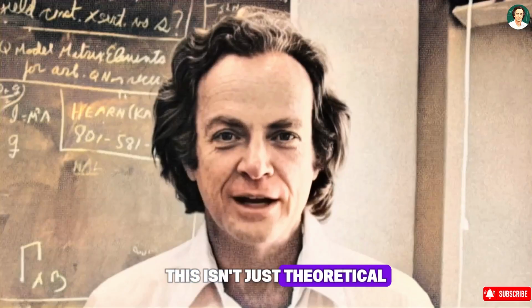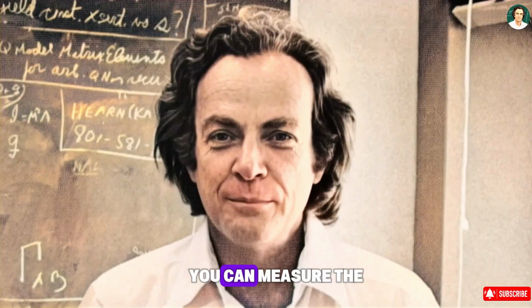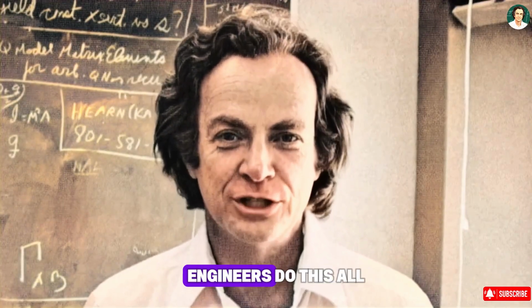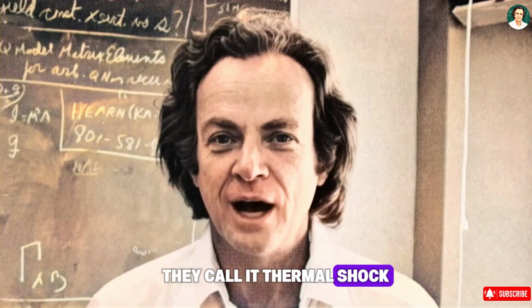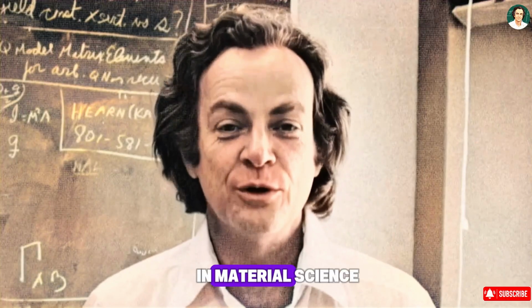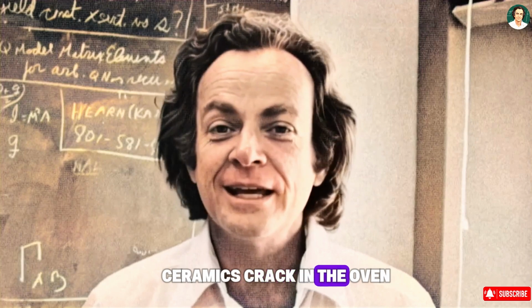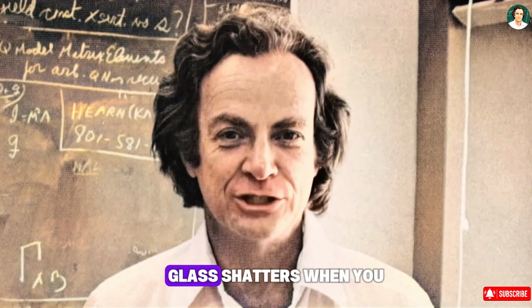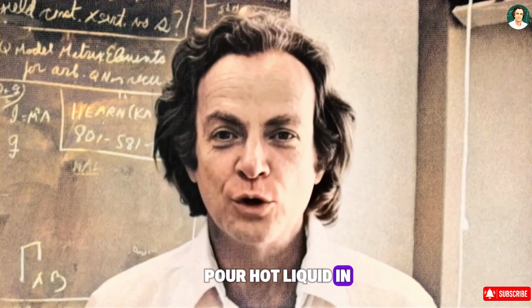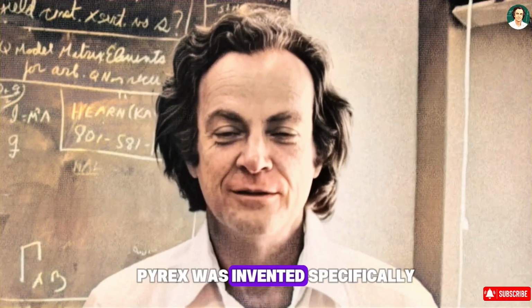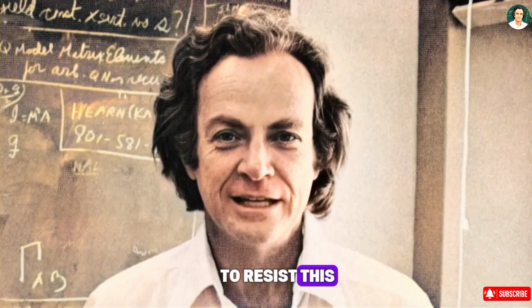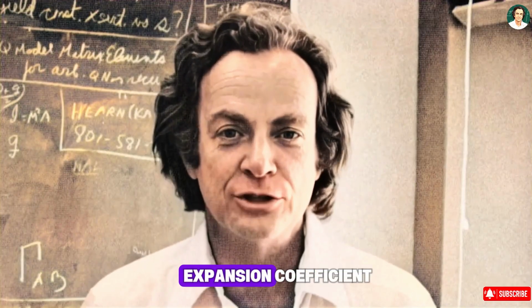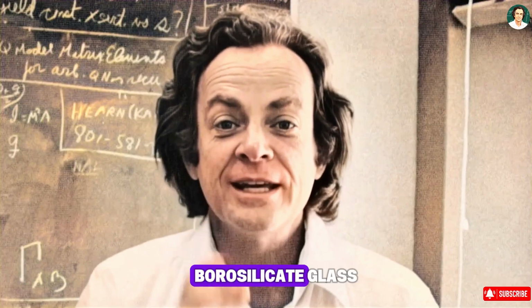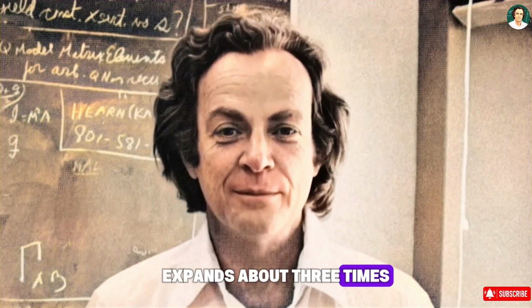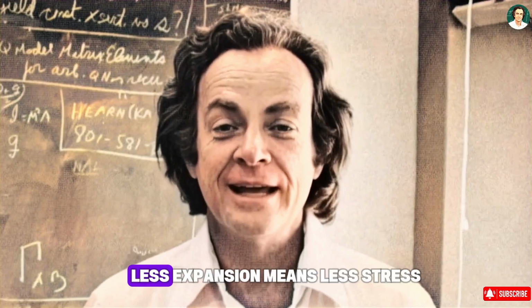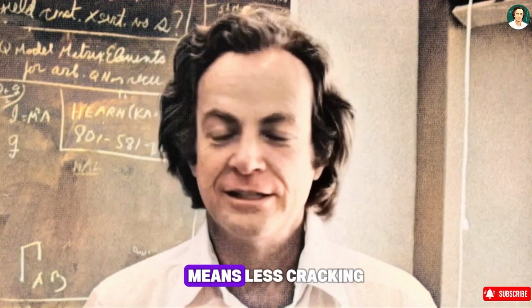Now here's the beautiful part. This isn't just theoretical. We've tested this over and over. You can measure the thermal stress precisely. Engineers do this all the time. They call it thermal shock. It's a massive problem in materials science. Ceramics crack in the oven for the same reason. Glass shatters when you pour hot liquid in cold glass. Pyrex was invented specifically to resist this by lowering the thermal expansion coefficient. Borosilicate glass expands about 3 times less than regular glass. Less expansion means less stress, means less cracking.